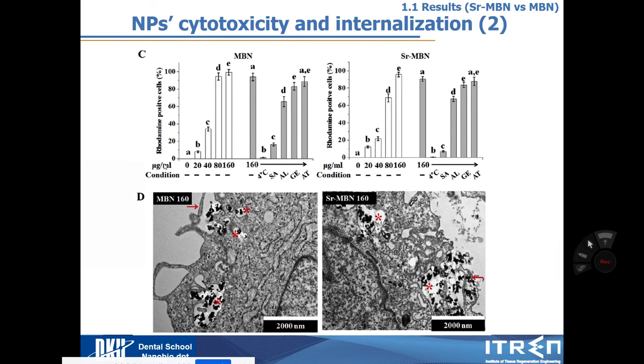And then I want to check how this nanoparticle is uptaken, the underlying mechanism. I found that without 4 degrees and sodium azide treatment, when the cell can use ATP, they can uptake the nanoparticle. But without ATP, after the 4 degrees and sodium azide chemical treatment, there is no uptake, which means the cell needs ATP to uptake this nanoparticle. And then over the concentrations, I check how much nanoparticle can be uptaken by the cell. When I treat 160 microgram per ml, they uptake around 100%, like this. And the same for MBN and strontium MBN: they are uptaken by the cell in an ATP-dependent manner.